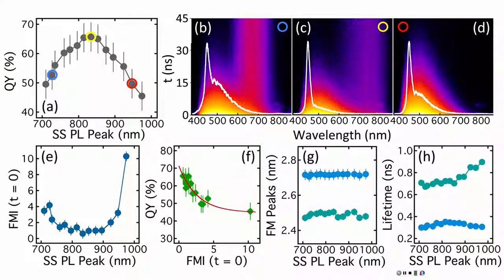Then as time goes on, what you start to see is a transition. This isn't a single state, right? And Andre knows what I'm talking about. This is a sort of a few discrete states, okay? At longer times, what you then see is the band gap emission, and it redshifts slightly with time. So this peak is going to move when you get to times between around 10 nanoseconds out to milliseconds. You're seeing this peak, and it's going to shift a little with time. But that all involves the actual band gap.